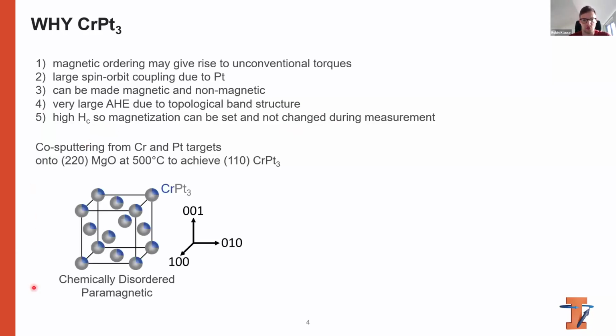To grow this material, we used co-sputtering from chromium and platinum targets onto 220 oriented MgO substrate at 500 degrees Celsius to achieve 110 oriented chromium-platinum-3. This gives us the chemically disordered chromium-platinum-3, where the chromium and platinum atoms are randomly distributed on the FCC crystal structure, and in this case it's paramagnetic.